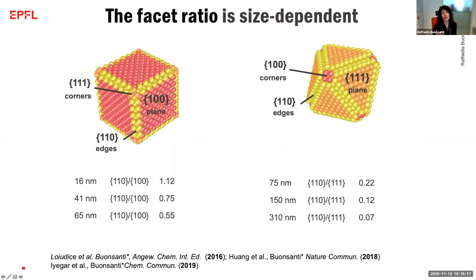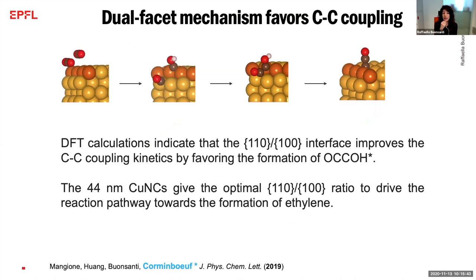Now, when we change the sizes, of course, we do change the surface-to-volume ratio, but what we also change is the ratio between facets. In particular, we change the ratio between the 110 facet and the 100 facet in the case of the cubes, and the ratio between the 110 and the 111 facet in the case of the octahedra. Why does this matter? Because my colleague Clemence Corminboeuf, a theorist, helped us understand that it is really this interface that is crucial for the C-C coupling, which leads to the formation of ethylene. Therefore, these intermediate sizes provide us with an optimal ratio to move towards the formation of this product.